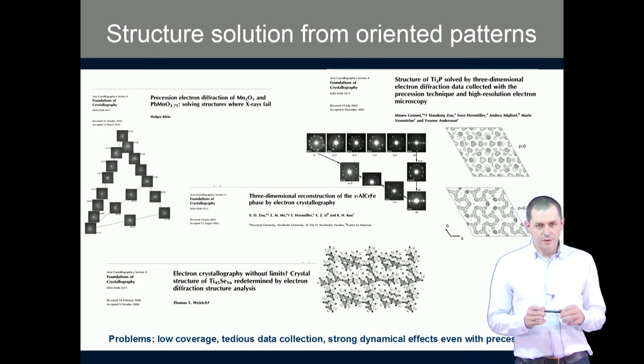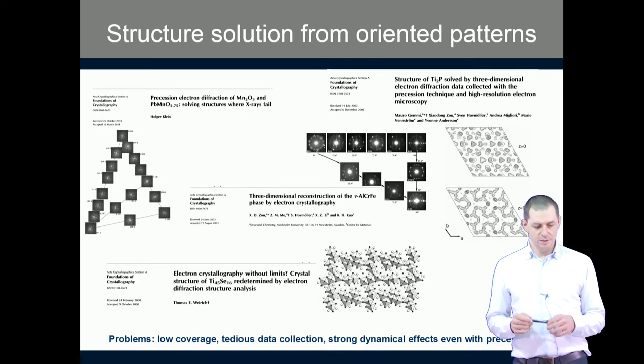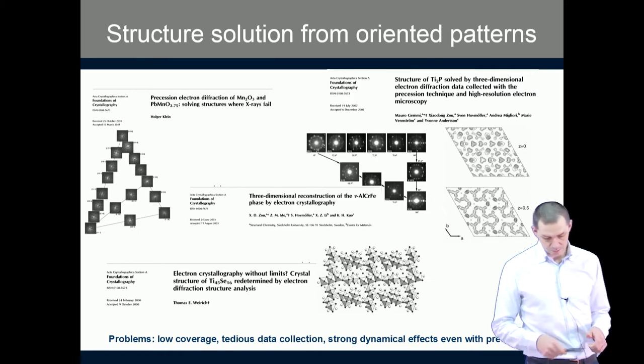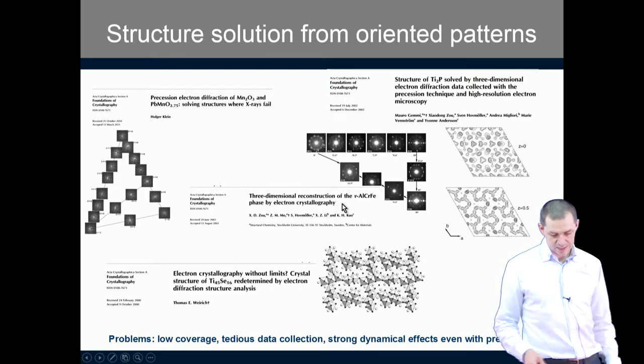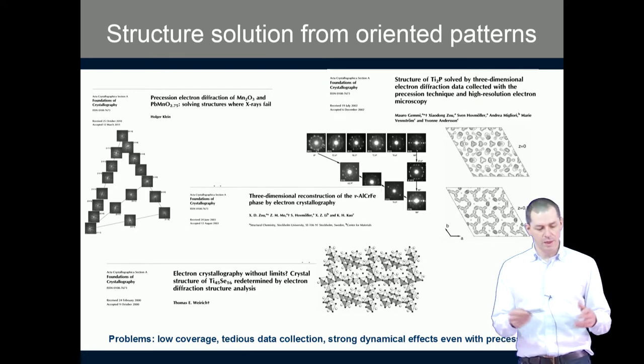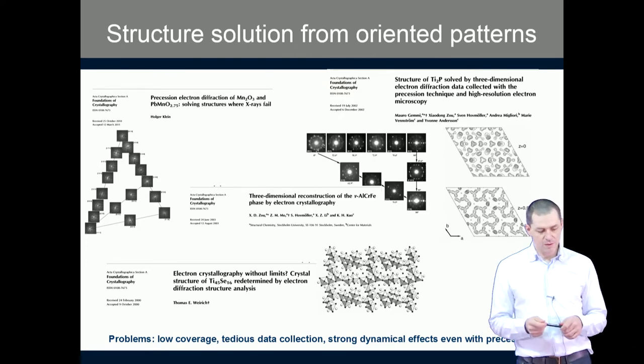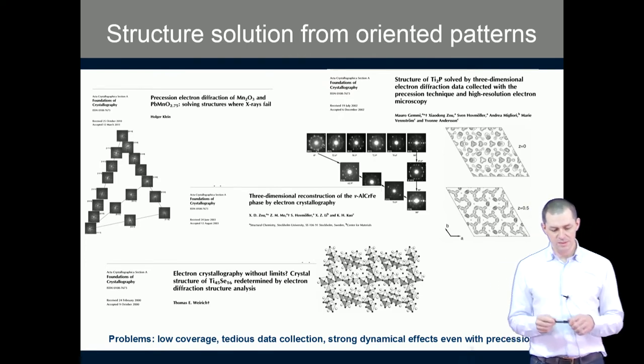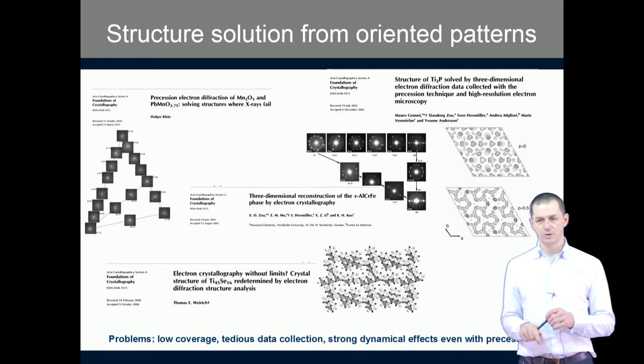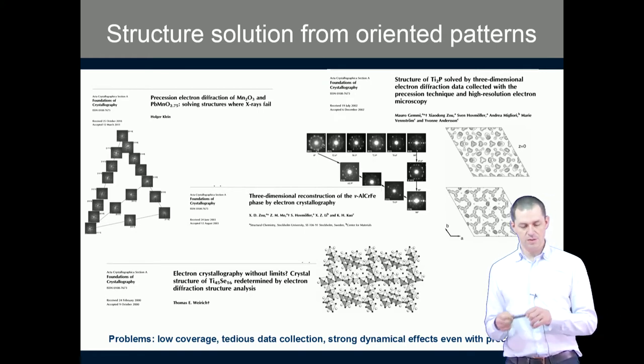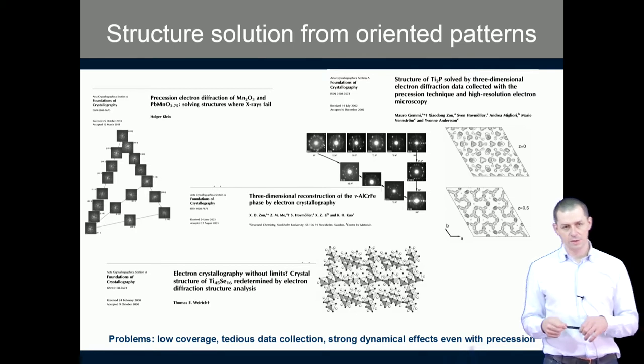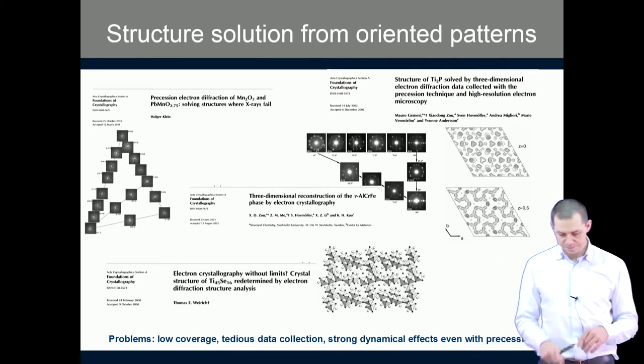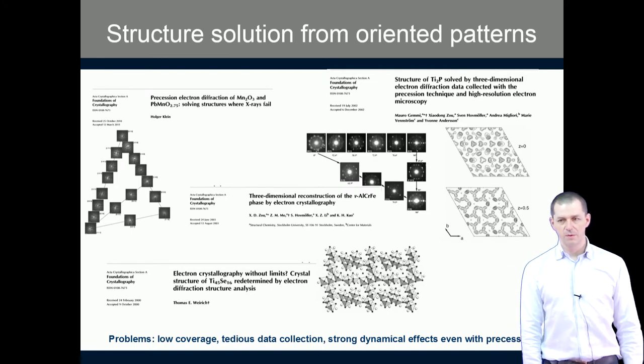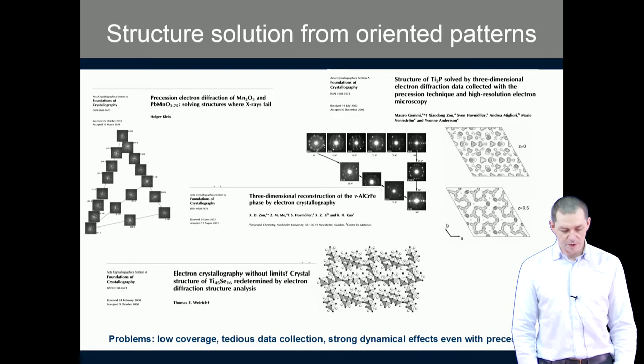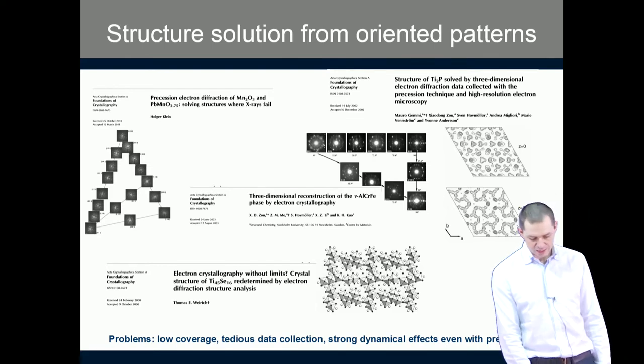Using oriented diffraction patterns, a number of structures, including quite complex structures like certain quasicrystal approximants, have been solved with and without precession, but it was still a tedious, long-lasting exercise. It is difficult to collect a large set of nice oriented patterns, and it was also difficult to extract the structural information from these sets of patterns. So it has not become a very widely used technique despite the successes demonstrated in these and other papers.